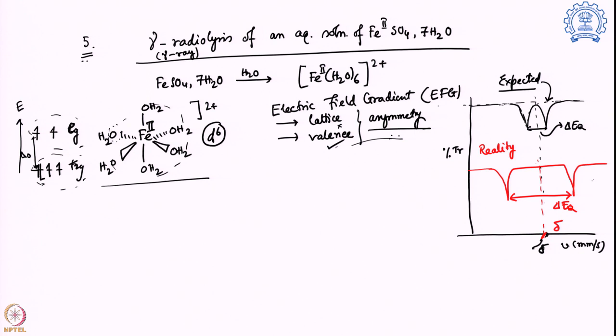So, why so? Because there is one other phenomenon happening over here, and that is known as the Jahn-Teller distortion. Because of the asymmetry present in the T2g level, that is going to undergo further splitting. And this particular energy gap is not going to help, but this one, you are gaining some energy from this configuration. So that is going to happen. So you will see Jahn-Teller distortion. Jahn-Teller distortion, and what is happening?